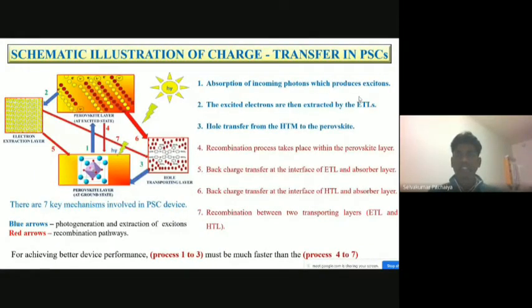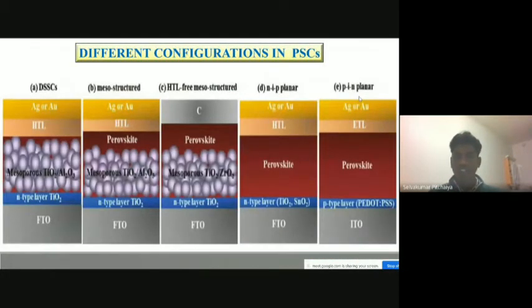And this is the schematic illustration of the charge transfer mechanisms in the perovskite solar cell, which includes 7 mechanisms. The first 3 are the most advantageous charge transfer mechanisms, and from 4 to 7, they are highly undesirable. They must be avoided so as to achieve higher efficiency in our device. These are different configurations in the perovskite solar cell, which is the successor of the dye solar cell. I cannot go into it; it is a vast subject, and from that we have taken this perovskite structure, and by placing various electron and hole transport layers and shifting them, we can produce different configurations in perovskite solar cells.